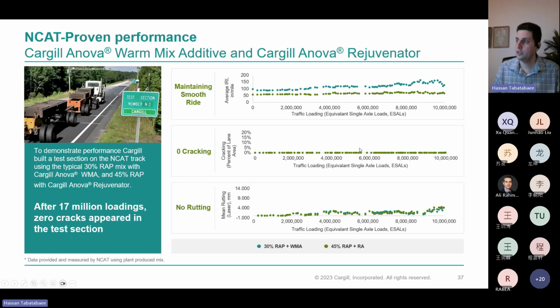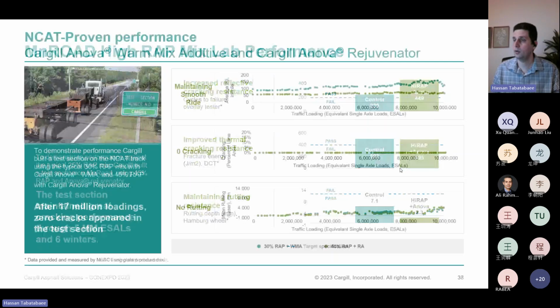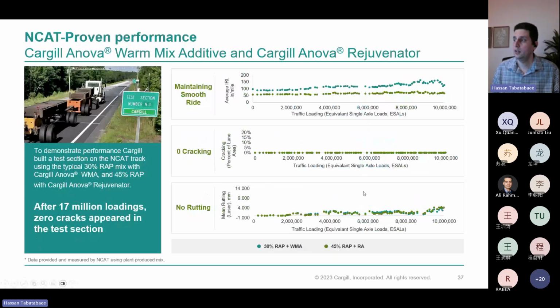However, as you can see, 0 cracks in both sections throughout this pavement testing. This is from the first 3 years, 10 million cycles, and I can tell you at this point, after nearing 20 million, there is still no cracking, and there was no significant rutting either, less than 5 millimeters of rutting. So very significant loading and nearly no distress or damage after more traffic than most highways would take in the US.